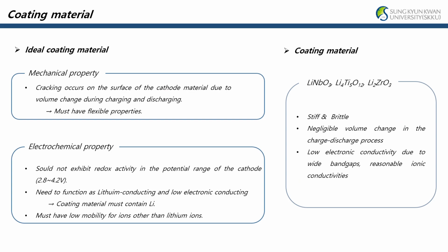The ideal coating material should have flexible properties to avoid cracking on the surface of cathode material due to volume change during charging and discharging. In terms of electrochemical properties, it should not exhibit redox activity within the potential range of cathode. It should also have low mobility of ions other than lithium ions. Materials such as LNO, LTO, and LZO with suitable properties are currently the most widely used cathode coating materials.